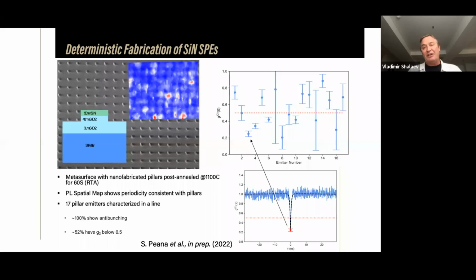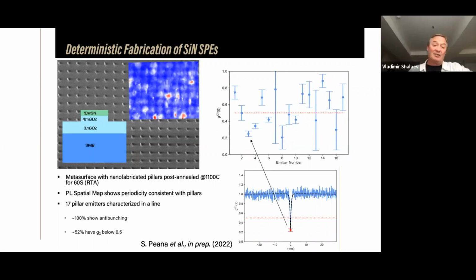They're statistical, meaning that they are described by a Poisson distribution, meaning that there's like 35% of single photon emitters, the rest are either zero emitters, zero photons, or more than one photon. Here it's clearly above 50%, which means that potentially it could be optimized so that the yield could approach 100%, meaning that every pillar would have just one single photon emitter. And that could make a difference for photonic-based quantum computing, which is the final goal.